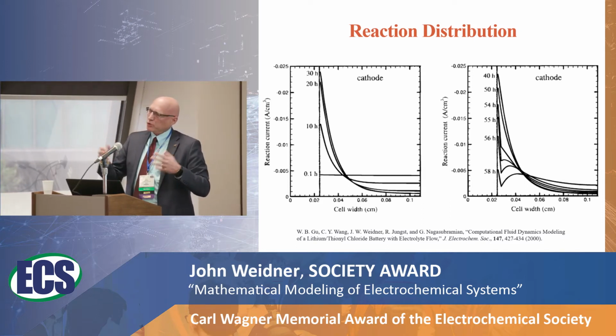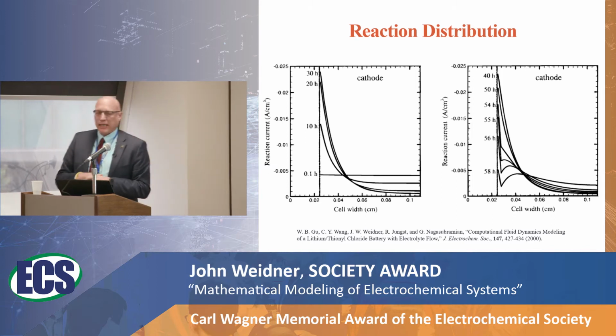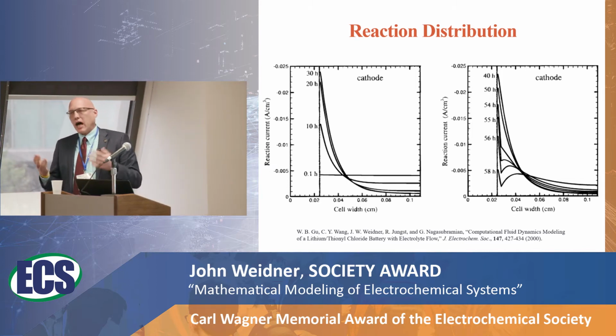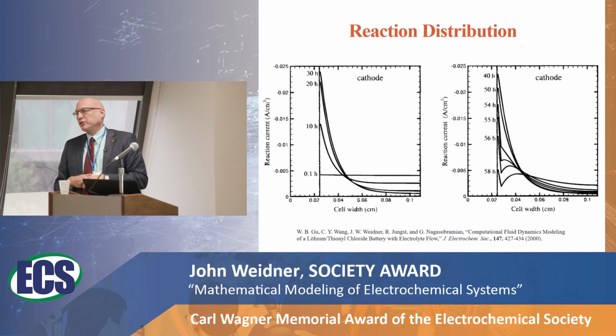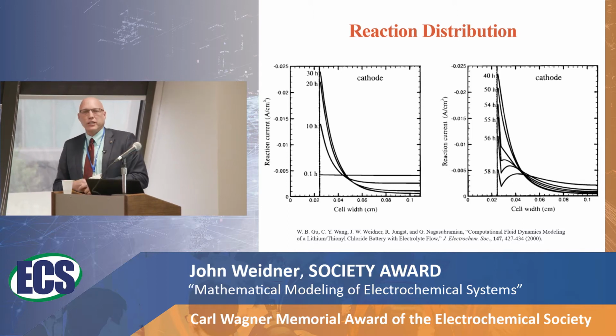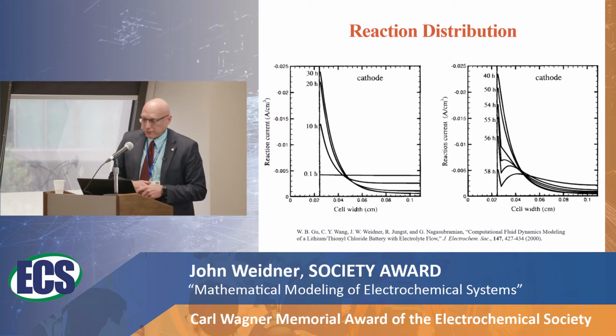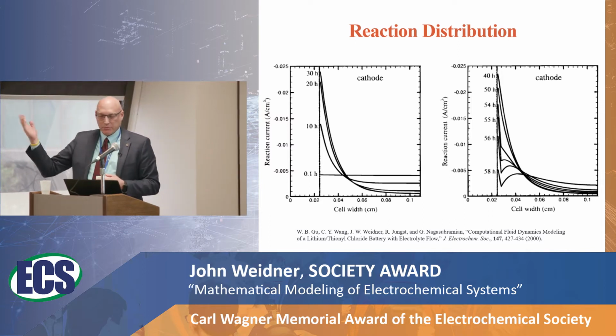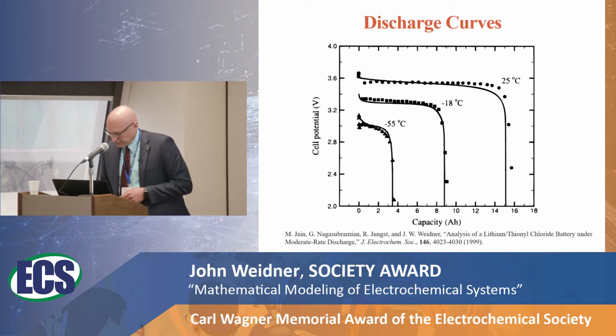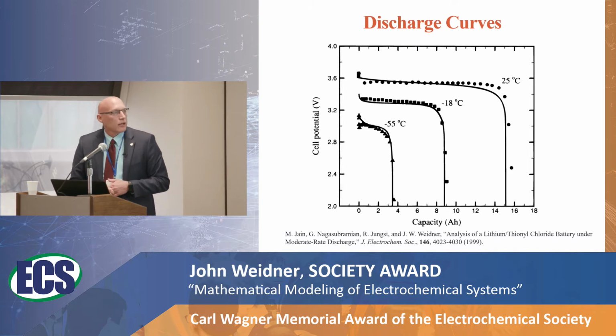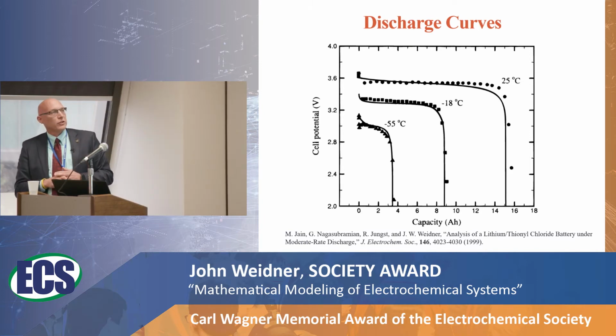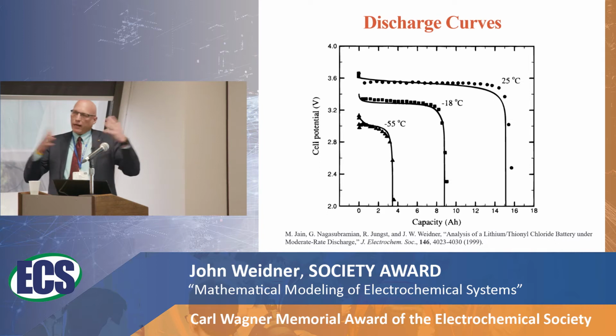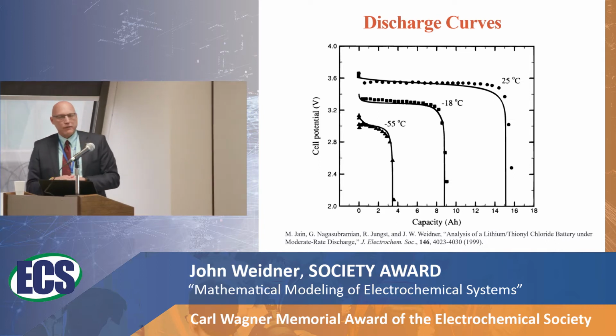And this was work that we did with Sandia National Lab. They had a lot of experimental data. They were interested in understanding these high energy density cells over a very wide temperature range, from minus 55 degrees Celsius up to even 75 degrees Celsius. So once again, a lot of data that we collected.